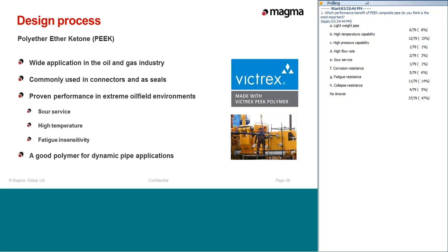Some of the things that were important to us when we went through that long process of identifying PEEK as the most appropriate material for a high-performance thermoplastic composite pipe: we looked at its track history in the industry, and we saw that it was widely applied within the oil and gas industry. It was commonly used in applications like connectors and seals, which really proved out its excellent chemical resistance and creep characteristics. And PEEK has a proven performance in extreme oil field environments, so it's very good at dealing with sour service, high temperature, and it has great fatigue resistance. All of these characteristics led us to believe that it really is a good polymer for dynamic pipe applications.